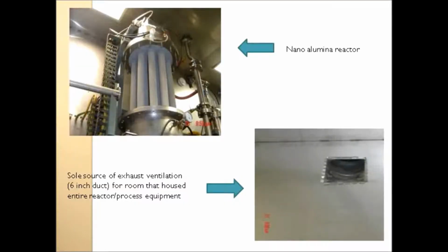Another example is a nano alumina reactor where they've got these cylinders that collect material inside the reactor. They're filtered, then they're shook, or reverse pulse jetted to blow the material off the filter and collect it on the bottom by a gravity feed. And it was funny in a sense that this was occurring inside a chamber, and this was the only exhaust ventilation duct that I could find that was designed to control releases inside of that operation.